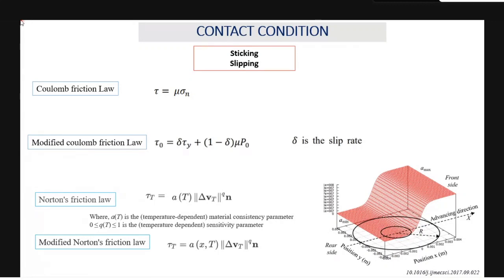So there will be a question: what to use? Actually, there is no standard. If you do a detailed literature review on these aspects, you can find some authors reported very good agreement with the experimental results with sticking. Some people have slipping. Even the same author in different years concluded that sticking works sometimes, and at other times says sticking and slipping is good, because a lot of other underlying phenomena are happening there. So the only suggestion is that you have to analyze all the contact conditions, and whichever gives the close agreement with the experiment, we can take that for the analysis. Okay, so this is the sticking and slipping phenomena.